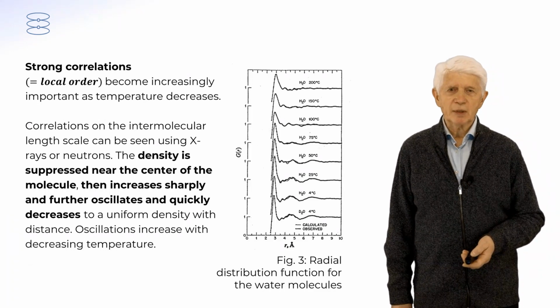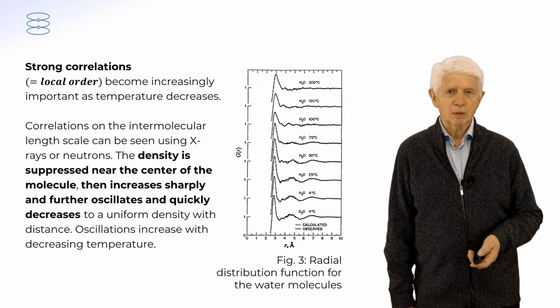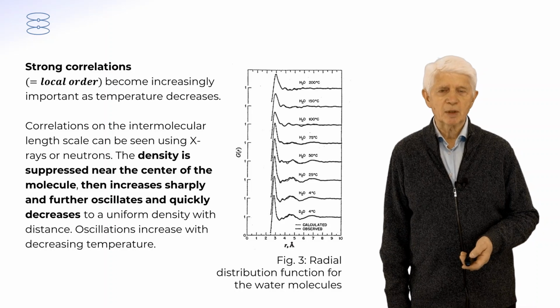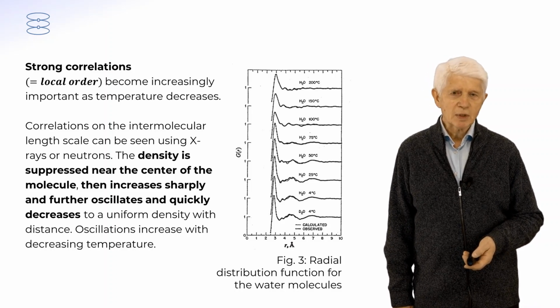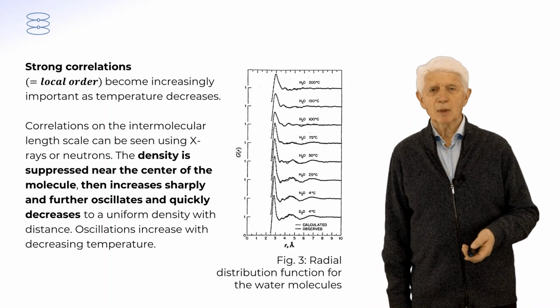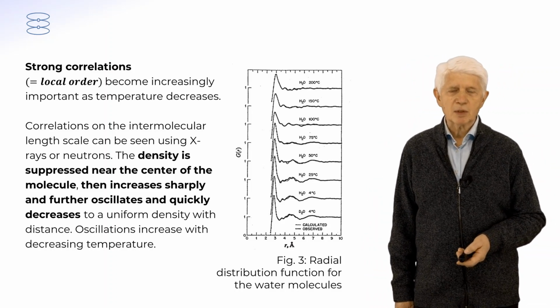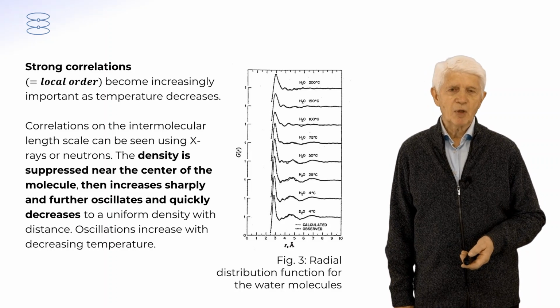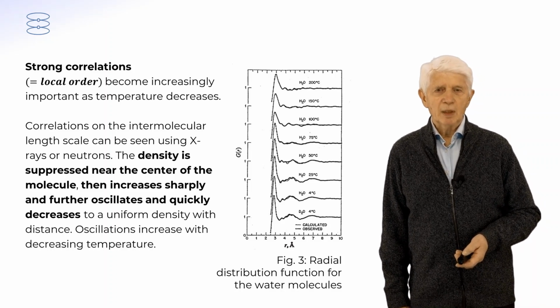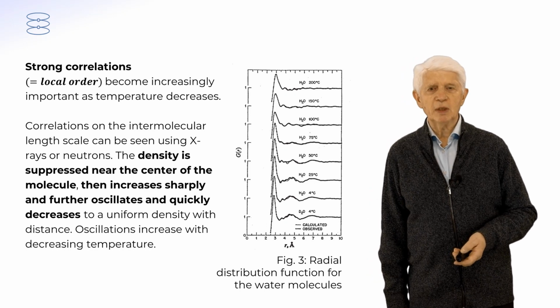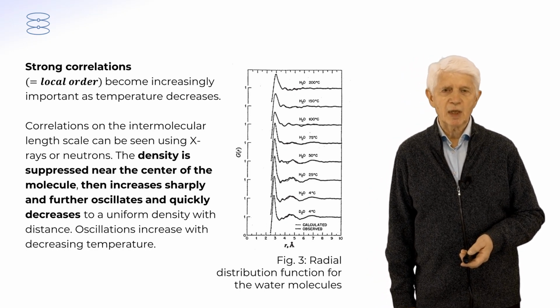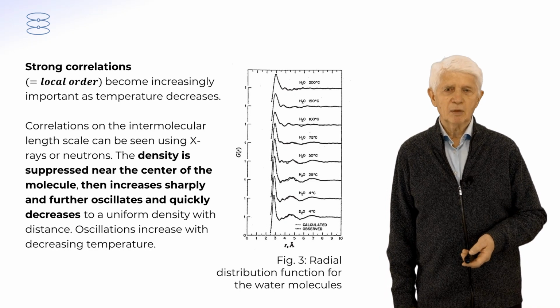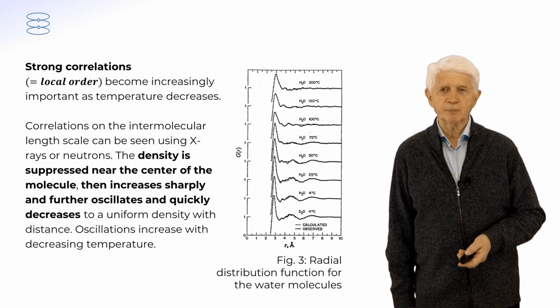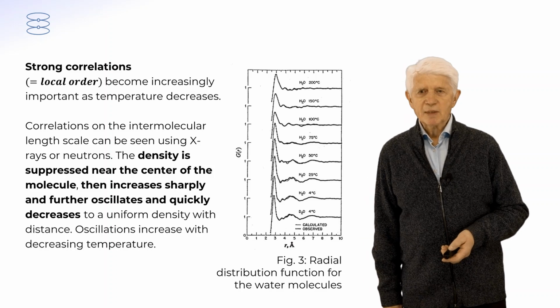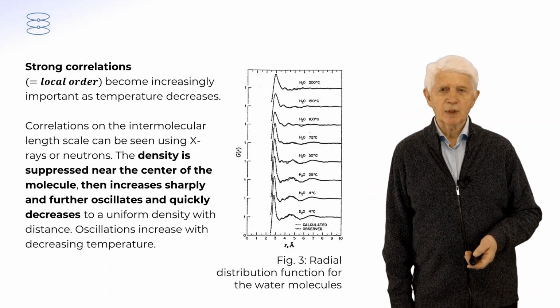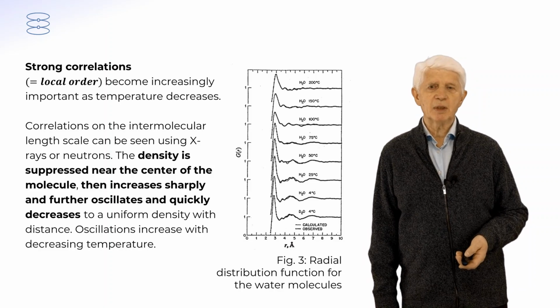These short-range correlations increase as you decrease the temperature, which is shown on the right-hand side. For water, these are quite well seen, you can see two oscillations at least, and finally the correlation function tends to unity. And this is again the important difference between the liquid and the gas. In a gas, the correlation function does not experience any oscillations. It's constant, it equals unity. So the density is suppressed near the center of the molecule, then increases sharply and further oscillates and quickly decreases to a uniform density.